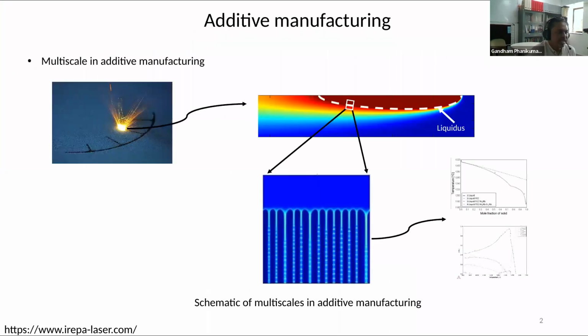So you see here, at what scale are we looking? We are looking at a scale where a laser is melting the powder and making the 3D component layer by layer. If you zoom into the region where it is getting solidified, this white dotted line is the molten pool, and the re-melting region has a temperature gradient. In that small box, solidification is happening normal to the interface, in the cellular mode. So that is the scale we are talking about: a micro scale compared to the component.